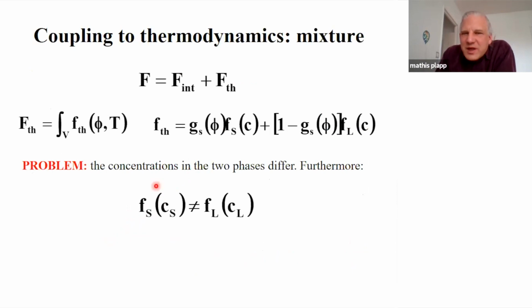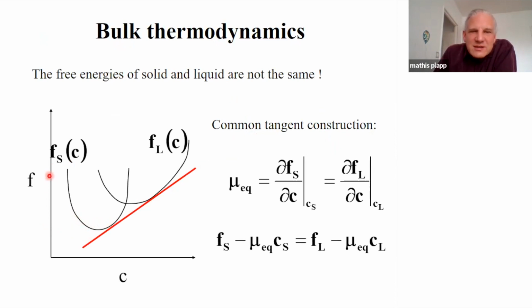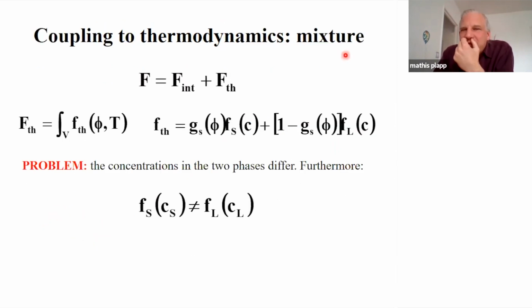Now, if I apply this interpolation here, first of all, I apply the free energy functions of the solid and of the liquid with the same composition, which just doesn't make much sense because coexisting solid and liquid don't have the same composition. And also I will use these free energy functions for values of the concentrations that will be far from any equilibrium composition, which means that all of this will go into the calculation of the thermodynamic free energy. And in addition, you can see from this curve that the two free energy densities are not the same. So I will get a driving force even at equilibrium, or in other words, the two contributions F thermodynamic and F interfaces in this formulation are not properly separated.